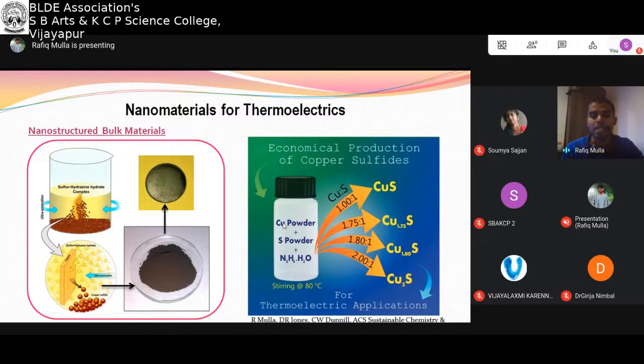And in fact, we are working on these nanostructured bulk materials. We are not exactly preparing nanomaterials. Our particles are a few hundred nanometers in size, but it is still not a standard bulk material. It is a nanostructured or microstructured bulk material, and from this material we can expect very low thermal conductivity while maintaining other parameters like good electrical conductivity and good Seebeck coefficient.